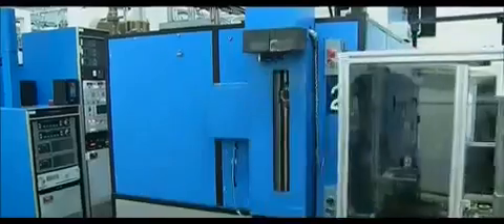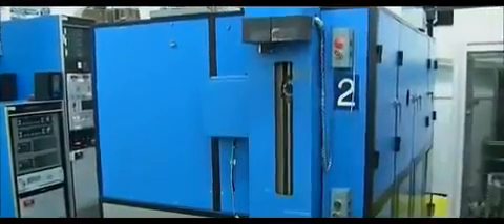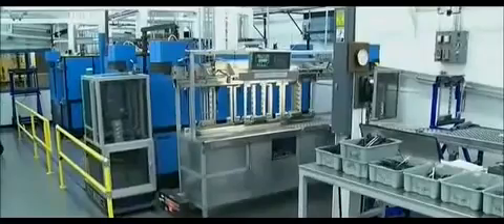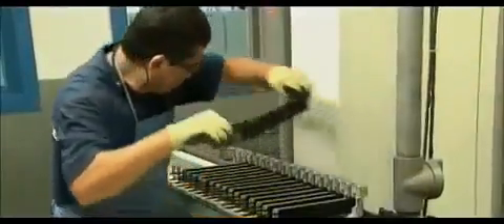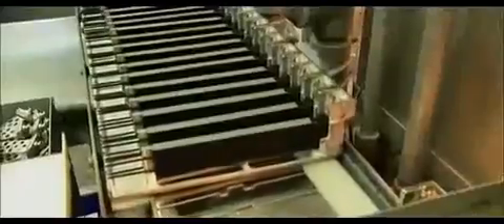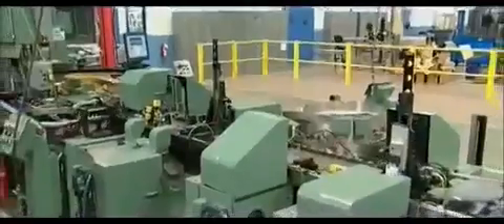Inside this vacuum chamber, Schick's Quattro blades are coated with the company's hardest available covering, a combination of titanium and man-made diamond. And inside a second chamber, a low-friction polymer film is sprayed onto the cutting edge. The first coating process basically makes the edge harder, and the second process basically makes the edge slipperier so that it glides through the hairs instead of pulling and tugging at them.